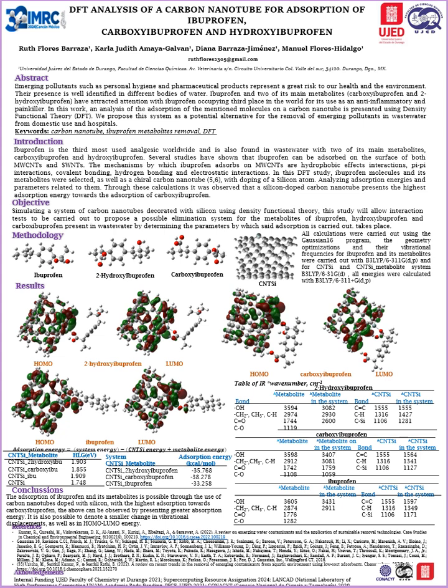Analyzing adsorption energies and parameters related to them, through population analysis, it was observed that the silicon-doped carbon nanotube presents the highest adsorption energy towards carboxyibuprofen. Simulating a system of carbon nanotubes decorated with silicon using density functional theory, this study will allow interaction tests to be carried out to propose a possible elimination system for the metabolites of ibuprofen, hydroxyibuprofen or carboxyibuprofen, present in wastewater, by determining the parameters by which said adsorption is carried out.